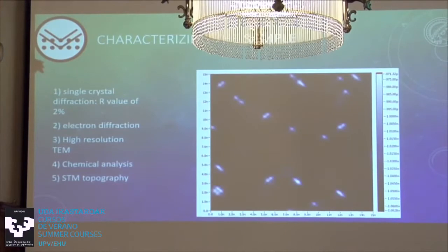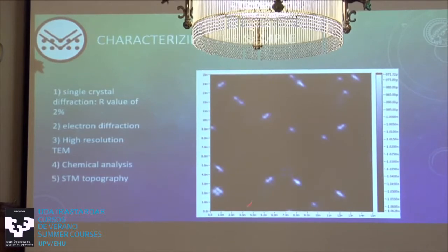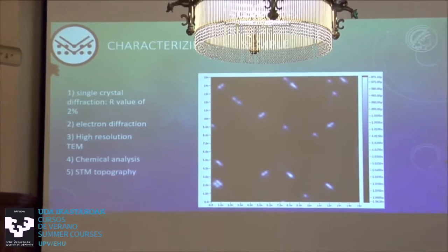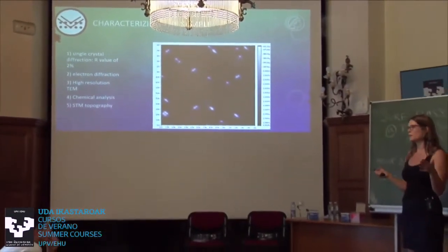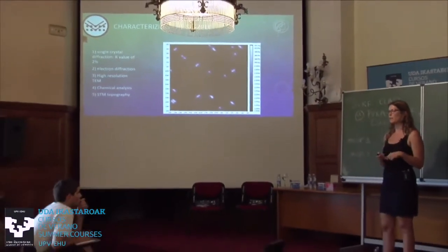And then lastly, we did some STM topography to get an idea about how many defects we have. So these bright spots are defects. And this scan is on the very first samples I grew before I improved the methods. And we already only had about one defect every 50 unit cells, and we could improve that. So this is actually a compound you can grow relatively defect-free.